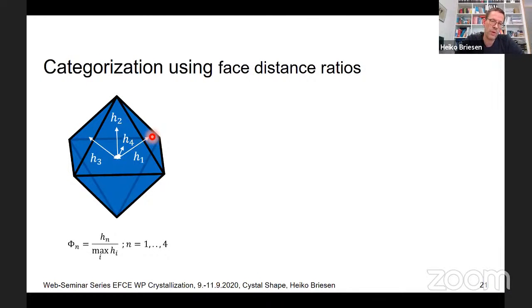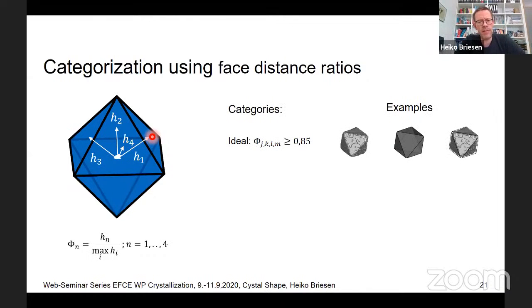What we did to get rid of the size information and to focus only on the shape information, we divided each of these numbers here by the largest H value of this set. So you always get a 1 and then a couple of values smaller than 1. The closer you are to the octahedron shape, the more similar they should all be to 1. And what we observed then is that there are different shapes in our sample.